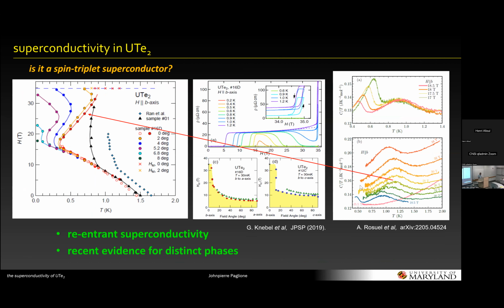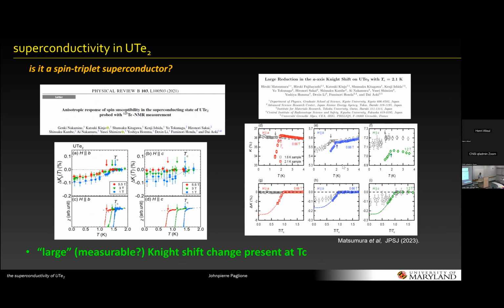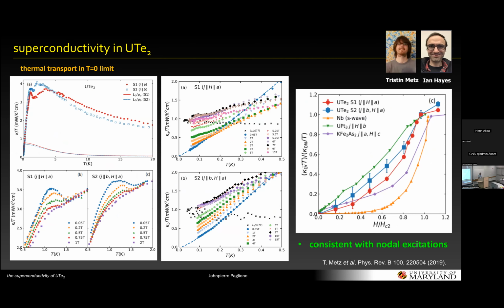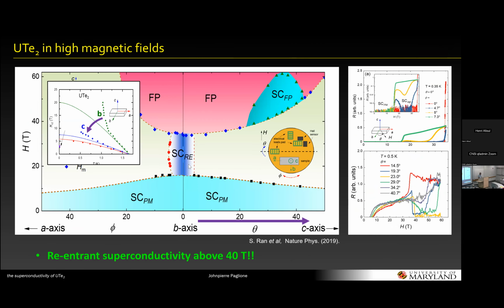And so that was studied, of course, by other groups as we progressed through this story. For instance, this is our data here, and it was pushed higher, and you can see that it goes all the way up to some cutoff that's believed to be a transition to a magnetic state, 35 Tesla. Sorry, this is out of order a little bit. So that's this phase right here that gets cut off. And then it was discovered by Ran at the Mag Lab that if you go off axis from the B axis and crank the field up, you have a reentrant superconducting phase that pops up above 40 Tesla.